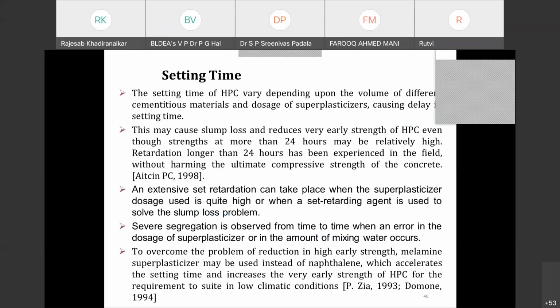Then coming to the setting or stiffening of high performance concrete, the setting time of HPC varies depending upon the type of the different cementitious materials you use, and also on the dosage of superplasticizer. Some of these superplasticizers, as you have seen, also act as retarders, so they cause a delay in the setting time. So before you use any particular brand, you have to be very sure to what extent of retardation it causes. This may cause slump loss also and reduces the very early strength of HPC, even though the strength at 24 hours may be relatively high. Retardation longer than 24 hours has been experienced in the field without harming the ultimate compressive strength.